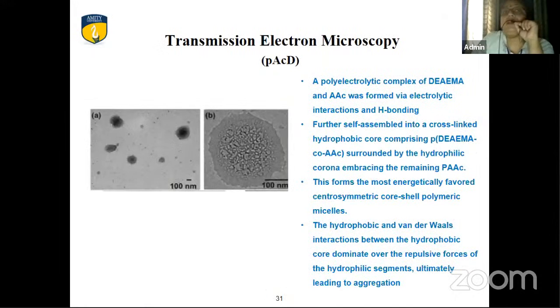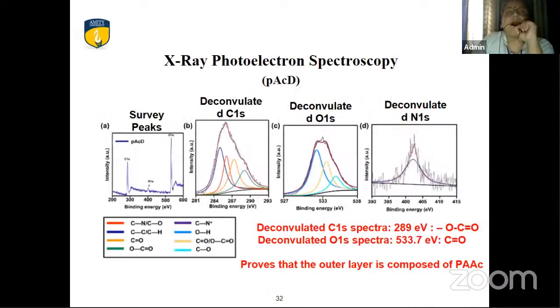Again, the question may be, okay, why GQD? Why not the polymer? Did you check with the neat polymer? Yes, we have checked. They only give rise to this polyelectrolyte complex showing micelles, and they are not giving rise to exotic nanostructures. That means exotic nanostructures are governed with the help of graphene quantum dots, which direct the self-assembly of these polymers, block copolymers, towards Kagome and Janus.